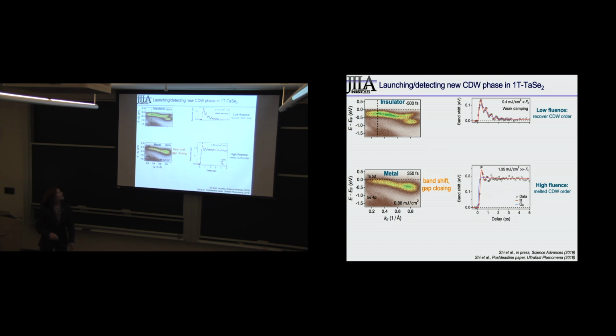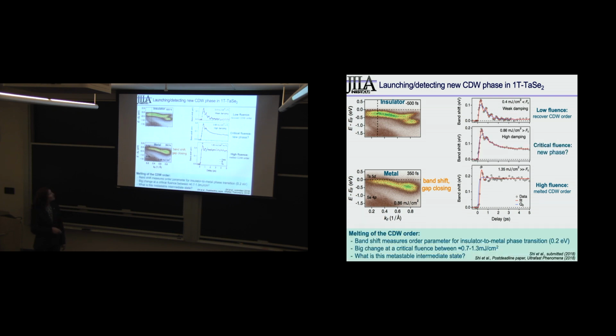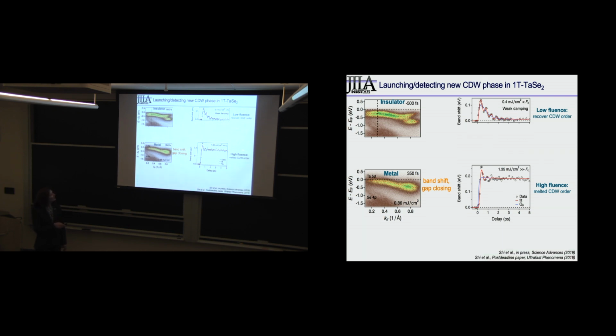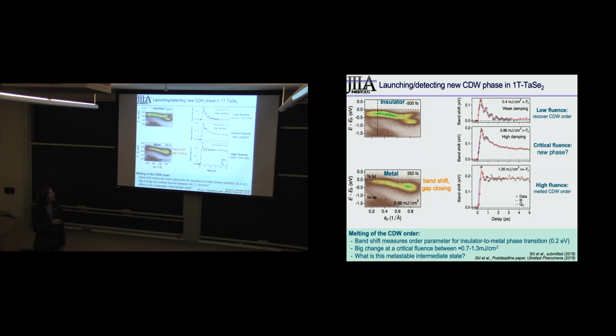So we did the experiment. We take the material in its insulating state, and then heat it very gently with the laser, and you get the band shift, so you almost melt it, and then there's a ringing because you've excited the breathing mode, but it recovers very quickly. Then if you heat it very strongly, you melt the order. Just what's shown here. So now it's gone to the metallic phase and the band gap is closed and the band is shifted. But if you heated it at an intermediate fluence, it went back halfway in between the insulator and the metal and stayed there for a long time.